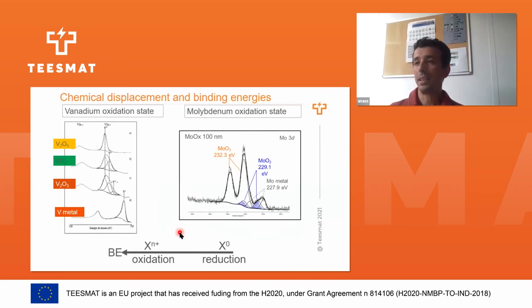The second part, I give another example, is the oxidation state. XPS can also give information about the oxidation state of materials. Here I give two examples. Let's start with the molybdenum oxide. This is 100 nanometers of molybdenum oxide deposited on a silicon wafer, and we can see that we have different signatures. The first peak corresponds to molybdenum metal. The second peak is molybdenum MoO2. The third peak is MoO3.